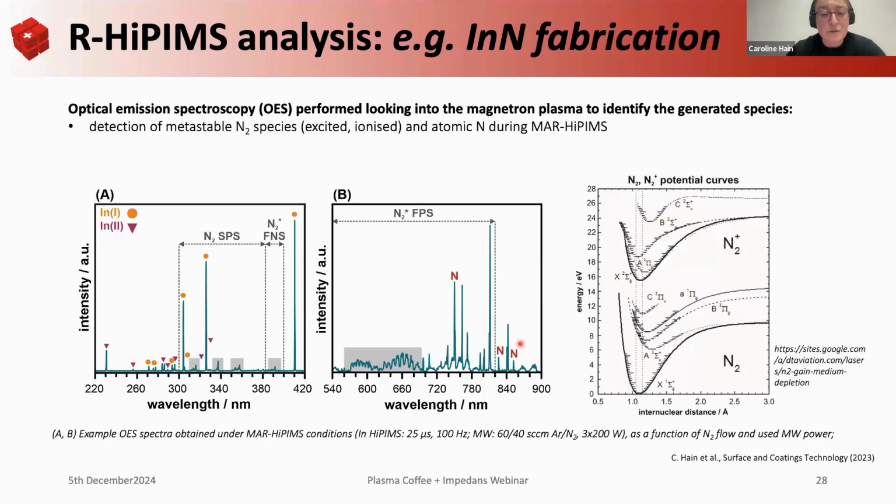So that can give us additional information into what's happening, right? So what we can do is follow the transitions in our state. For instance, if we look here, we can learn about the ionization energy required to go from molecular nitrogen to the ionized molecular state. So we look at the ground state, and there would be just under 16 eV required to ionize molecular nitrogen.